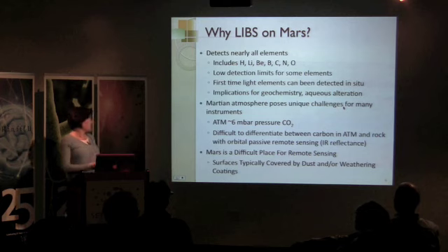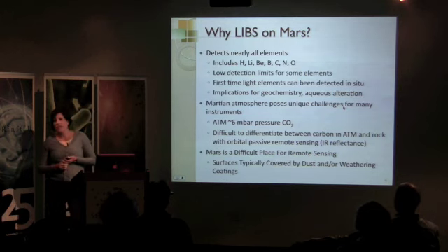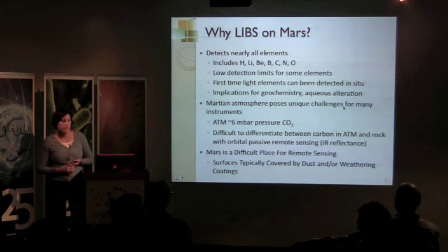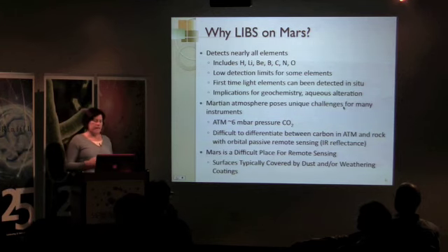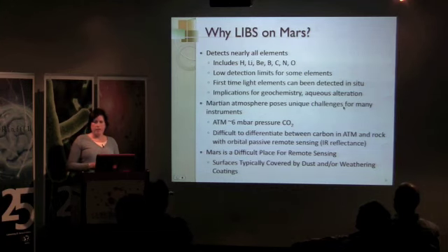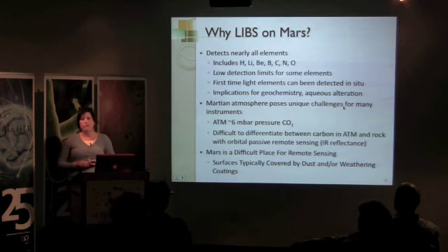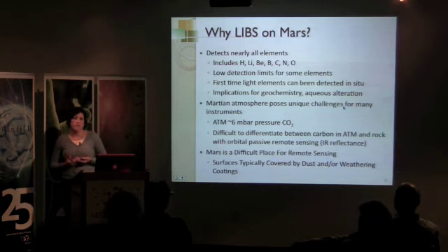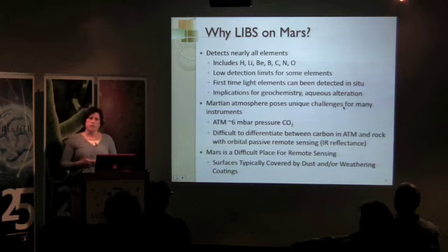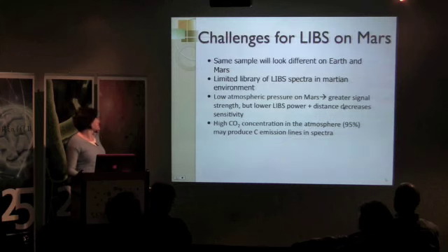The Martian atmosphere poses unique challenges for many of the instruments, both satellite-based instruments and other surface instruments. And these are things we have to address when trying to get ChemCam ready. And also, another advantage of LIBS, as I mentioned earlier, is that because you have this ablation capability, you can remove dust coatings on grains or on surfaces and potentially get down to a less altered or more pristine sample.